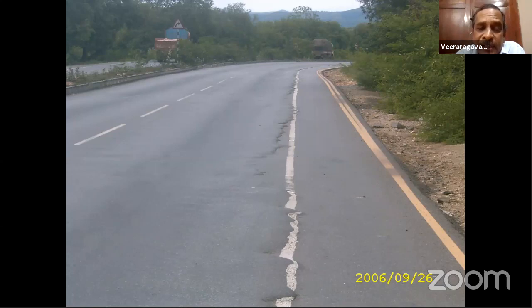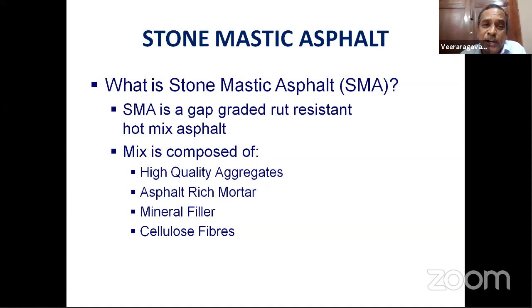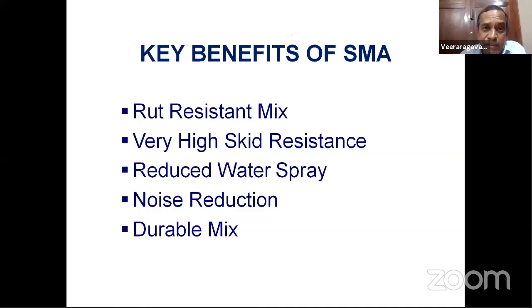What we found is that even though BC is likely to perform better on a government section, BC shears off. So BC is not the layer to be adopted. We found that SMA can be adopted. SMA is a gap graded mix, a rut resistant mix. It consists of high quality aggregates, asphalt rich mortar, mineral filler, and cellulose fibers. It's a rut resistant mix.